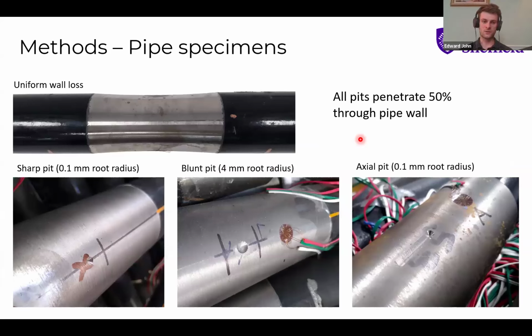So we added a series of different sizes and shapes of artificial pits to the pipe. There's been some previous research that's shown that the residual strength of the corrosion product is effectively negligible compared to the iron. So we could replicate these pits by just removing iron through a machining process.